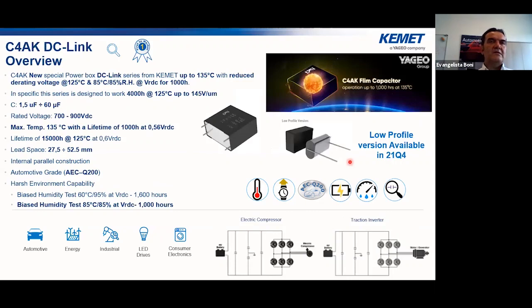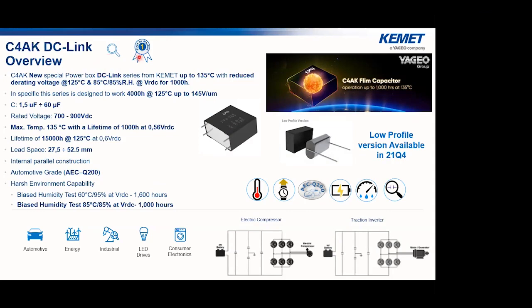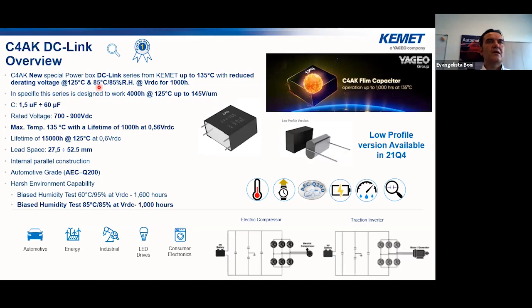Here we have the new outstanding C4AK product, the new DC-Link. Very special. This is the first on the market. This is a capacitor that can work up to 135 degrees, can work for 4,000 hours at 125 degrees, up to 145 volts per micron. So it's really a great achievement.